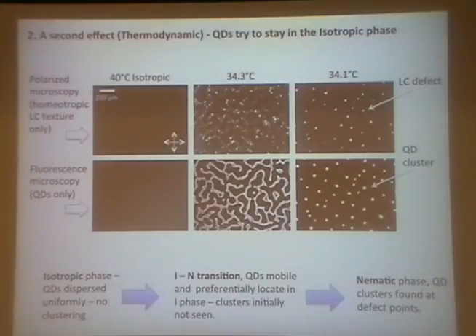So it doesn't really follow the domains of the phase growth at all. When we reheat to isotropic, you start to see a diffuse halo around the cluster. It gradually gets bigger. Imagine it just diffusing out. And that goes with the X-ray results, where it takes a while for this peak to disappear. It takes many minutes, and we have to do multiple scans before this peak starts to disappear. So diffusing back out of the cluster is much slower than this effect where we push them into the cluster.